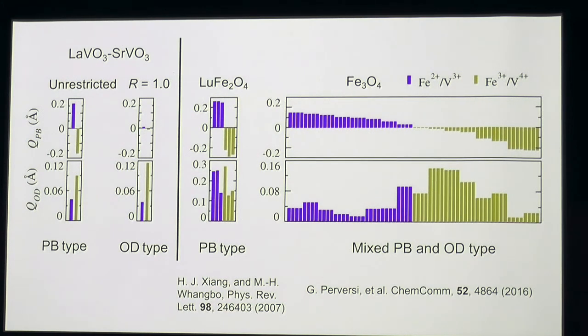And as we demonstrated before, its polarization cannot be flipped by an external electric field, which explains why we cannot observe polarization flipping in experiments. However, magnetite is a little different. Here, we plot the magnitudes of the 64 atoms in the primitive cell, which are involved in charge ordering. We can see for several atoms, their polyhedral breathing magnitudes are very tiny, indicating that for such polyhedrons, the characters are off-center displacement. And as we mentioned before, for such a type of charge ordering materials, its polarization can be flipped by electric field.